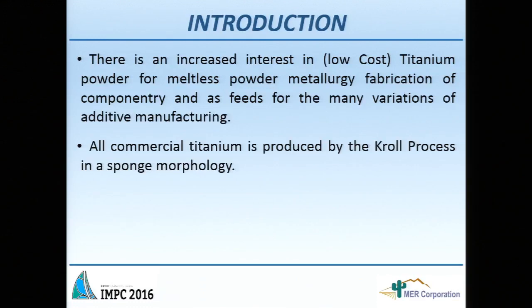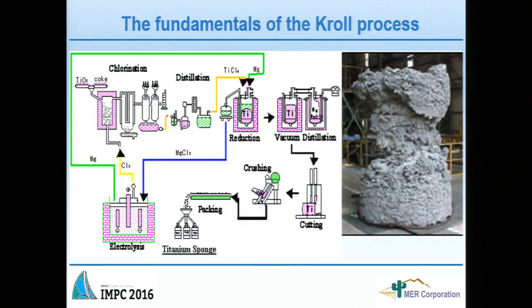But most of the titanium produced today commercially is from the Kroll process. So to understand how we can reduce the cost of titanium powder, we need to look at the fundamentals of the Kroll process. And this is a schematic, and it's a fairly complex process. This is a 10-ton titanium billet produced by the Kroll process. You have titanium oxide plus carbon. You chlorinate at high temperature. You produce the TiCl4, which is a tickle, and then you have to distill it to remove the iron chloride impurities and so on, and then you put it in a batch reaction, and you add magnesium to reduce the tickle to titanium and magnesium chloride, and the magnesium chloride is recycled to the magnesium cell.